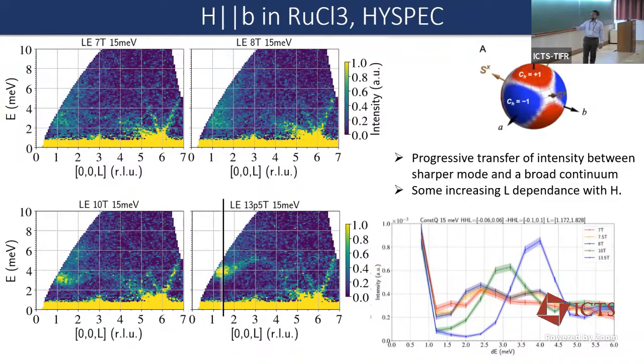And here also at 7 Tesla, we see these cloudy modes and no long range order. So that is very reminiscent of having a spin liquid state. And then what happens is that as you apply a field to 10 Tesla, this new mode starts to coalesce and develop. So this is very fresh data. We took this data basically at the end of July. So this we thought is remarkable. What is almost happening is that you have this continuum of scattering and that's getting slowly pushed to a mode, which is building up right here.